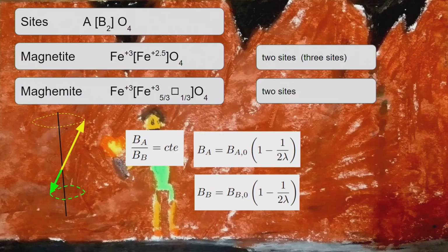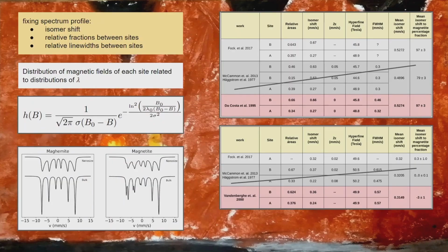Then we have in our samples magnetite and maghemite, and we have two sites for magnetite and also for maghemite. So we will have different hyperfine fields for each site, but the volume of the sample and the superparamagnetic moment are oscillating in the same way. So the hyperfine field of the irons in tetrahedral or octahedral sites reduce in the same way. So we will use that to say that both spectra should reduce in the same ratio. In that way, we are able to have a distribution.